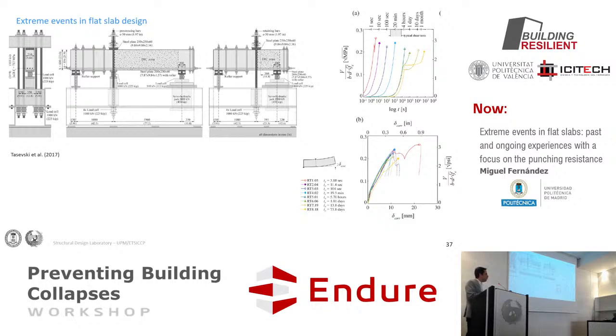But it was interesting because, to be honest, we couldn't load faster, because you are not capable of putting so much load in the hydraulic jacks in less than 1 second. At least we were not capable. That's the limit that we could use experimentally. But it was good because it was basically what we see in column removal cases. And what we saw is that the strength was rather constant.